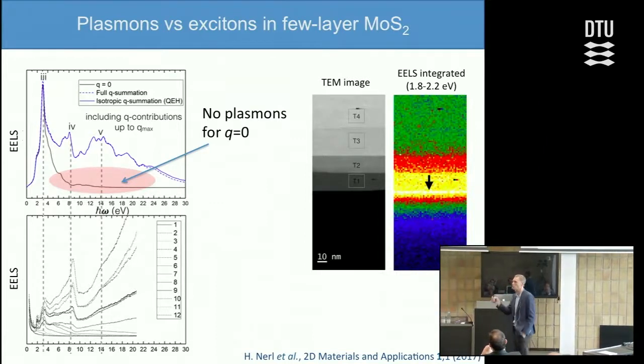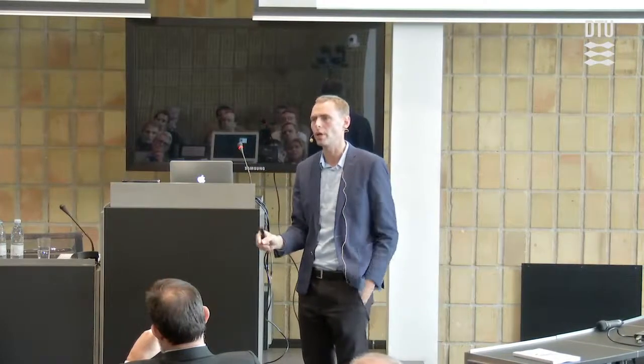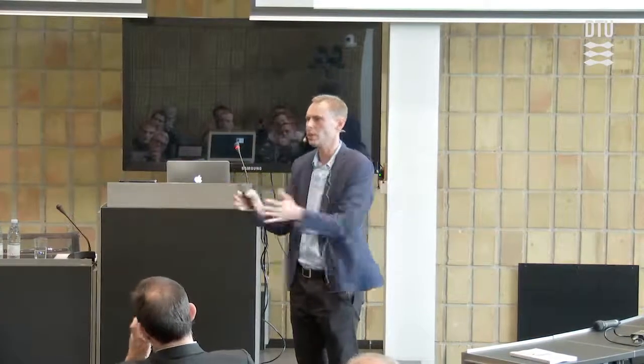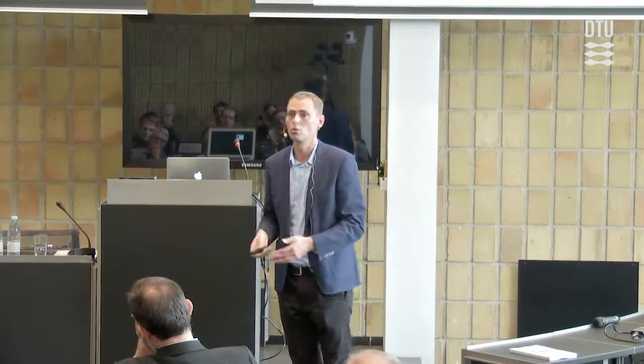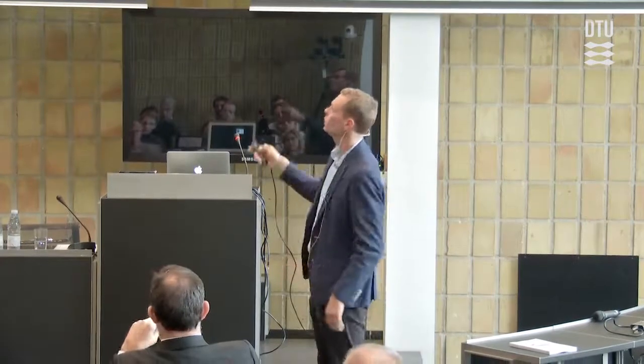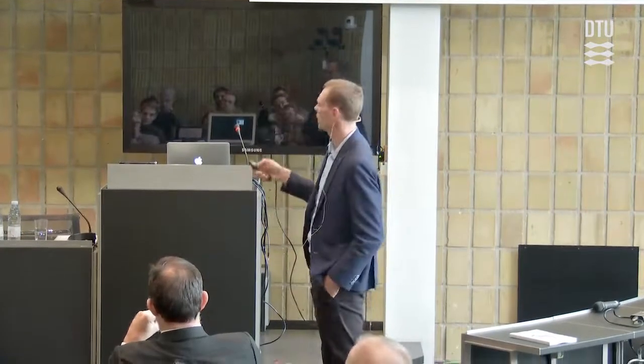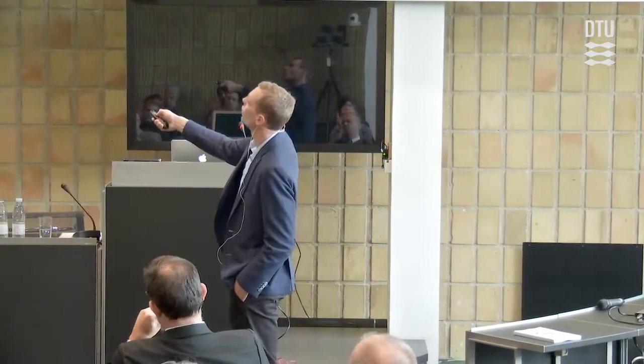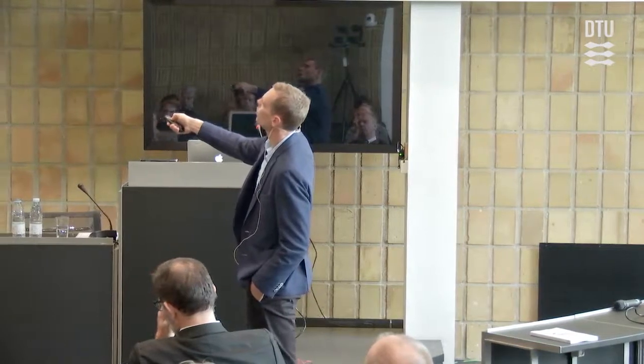At this point, we have to remember that a very localized electron beam is not a plane wave in the lateral dimension—it's localized, so it has all kinds of momenta in plane. So to reproduce the EEL spectrum of a localized electron beam, we have to sum over all the Q values. Then we get the blue curve.